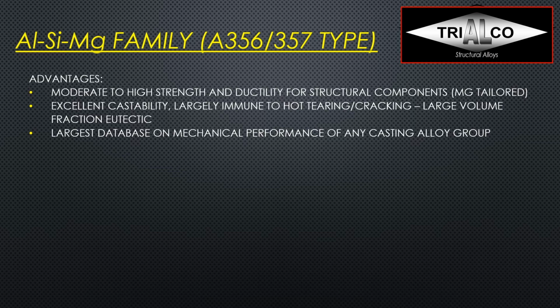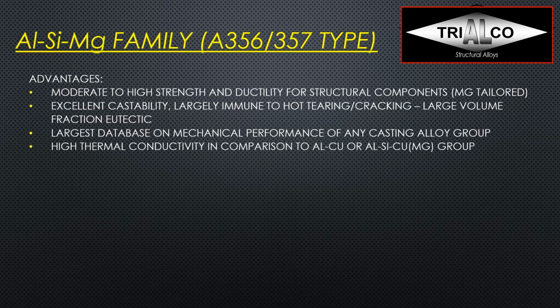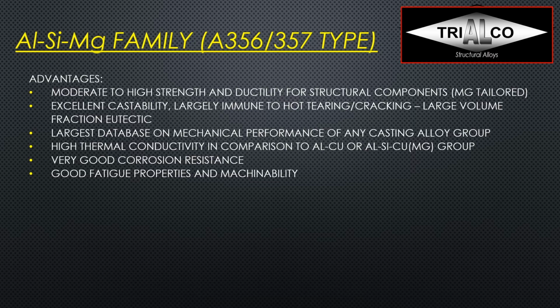So it makes it very easy for a product designer to use one of those alloy types to design their parts. They also have high thermal conductivity in comparison to the aluminum copper or aluminum silicon copper alloy. That makes it very attractive for certain applications as well. And they have very good corrosion resistance because they have no copper in there or very low. It's just an impurity. They have good fatigue properties and machinability, but their disadvantages are they must generally be heat treated to achieve high strength and hardness.